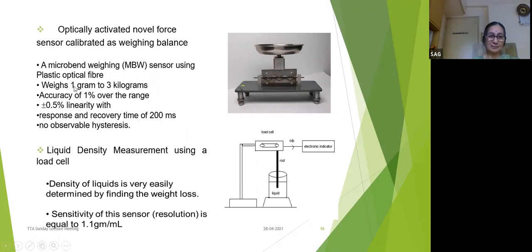The range of the sensor is 1 gram to 3 kilograms. Accuracy is of the order of 1% over the range with plus minus 0.5% linearity. Response and recovery times are 200 milliseconds, and there is no hysteresis observed. This is the one which was developed, but we could not go for the industrialization of this. Then liquid density measurement using a load cell. The density of liquids is very easily determined by finding the weight loss. The weight loss is found by a load cell, and the sensitivity of this sensor is 1.1 gram per milliliter.